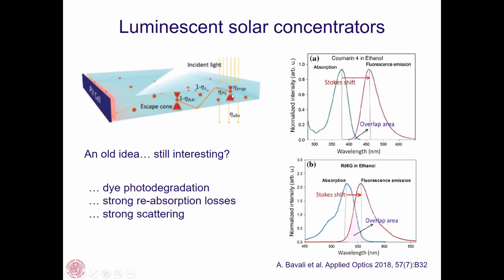Reabsorption occurs because part of the light emitted by the nanocrystals can be reabsorbed by the other nanocrystals or dyes, while the strong scattering is mainly generated by the matrix. The scattering issue can be avoided by using the PMMA matrix, while one of the best ways to remove the strong reabsorption losses is to increase the Stokes shift of our materials.